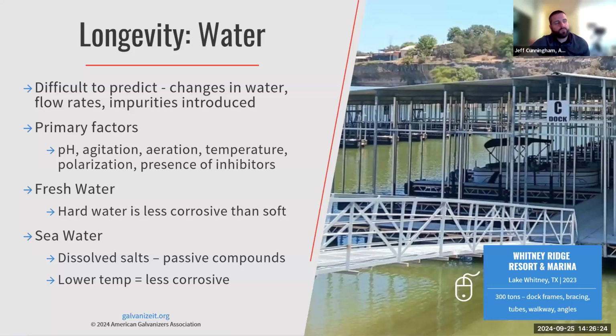Longevity in water, similar to soil, it is just difficult to predict. Changes in water, flow rates, impurities introduced. Primary factors are going to be similar: pH level, agitation, aeration, temperature, polarization, and presence of inhibitors. Freshwater, a good rule of thumb with that is hard water is less corrosive than soft, just because of the added chemicals they put in soft water.